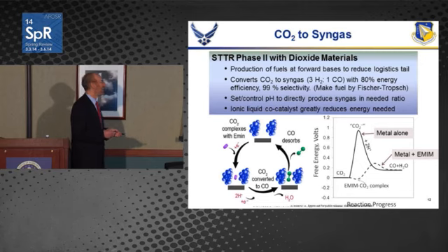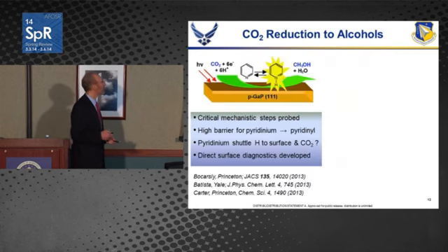Within this STTR, with the help of Dana Delott, they're going to be looking at what is actually going on at the surface of these electrodes, using methods like sum frequency generation to probe what's going on at the surface, to see whether or not the CO2 is complexing with the ionic liquid in a way that's reducing the barrier for this process.